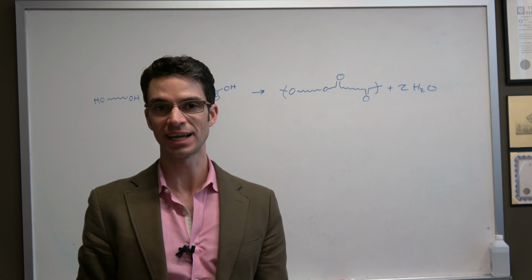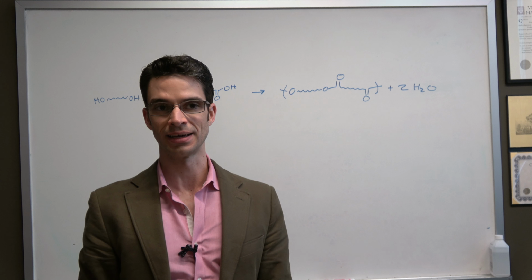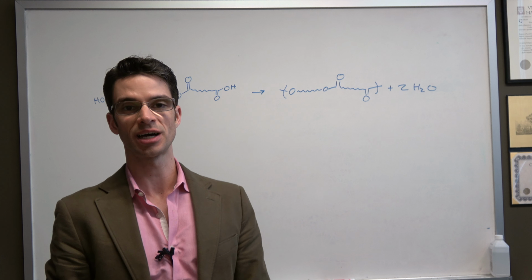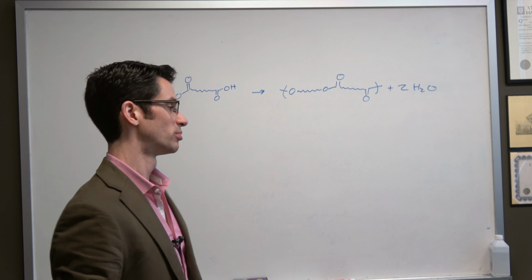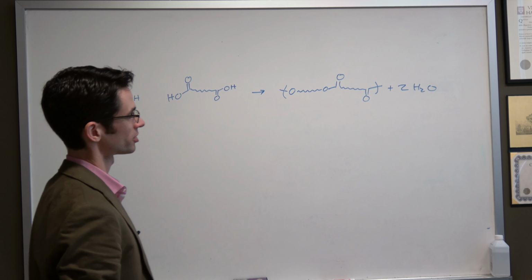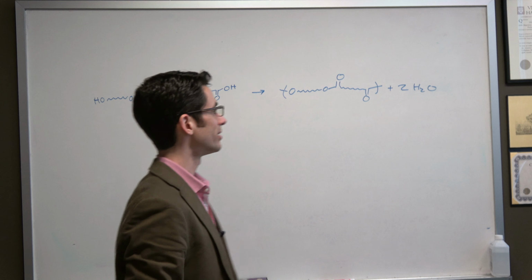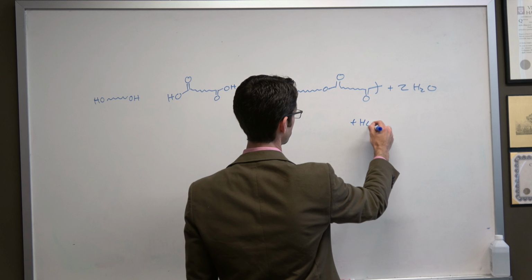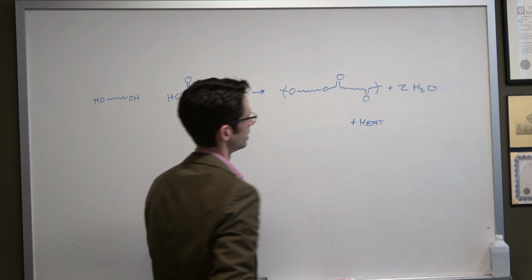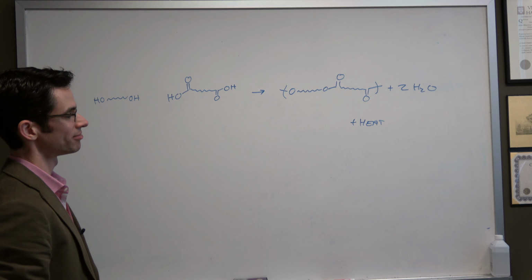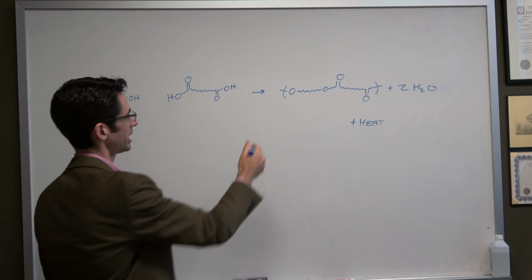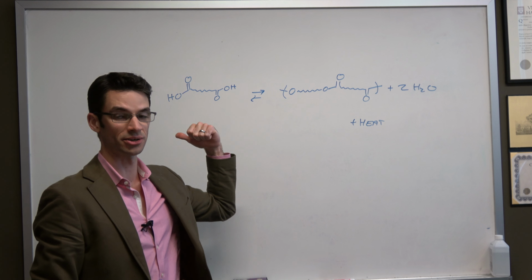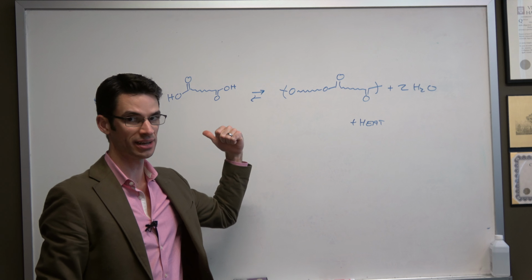Usually it's done in a vacuum oven, in a laboratory scale synthesis. You do it in a vac oven with the heat cranked, and you put a high vac with a water trap to trap the water. Now, even though this reaction is exothermic, one would think that if you added heat to this reaction, you'd shift the reaction back over here.